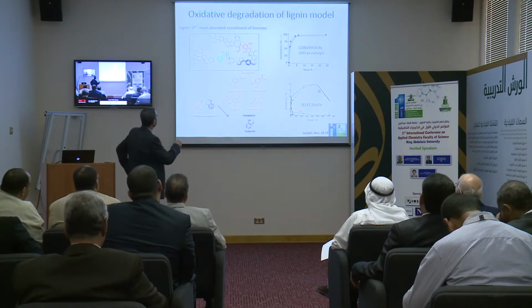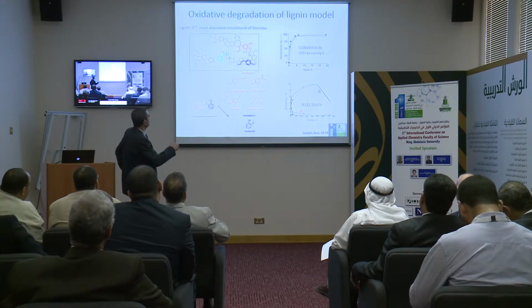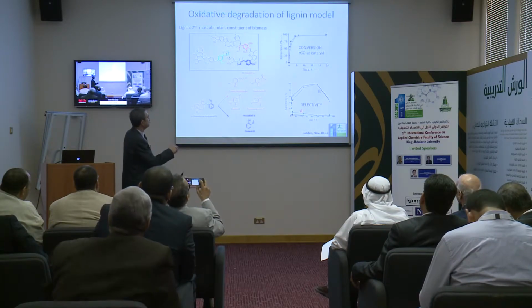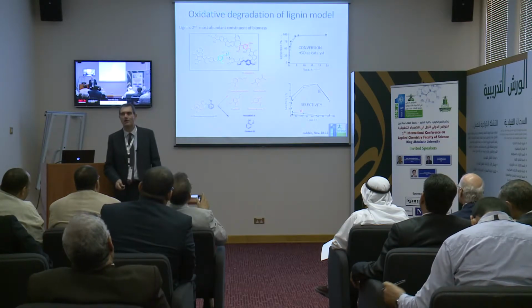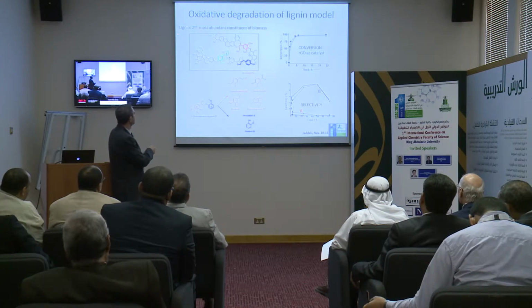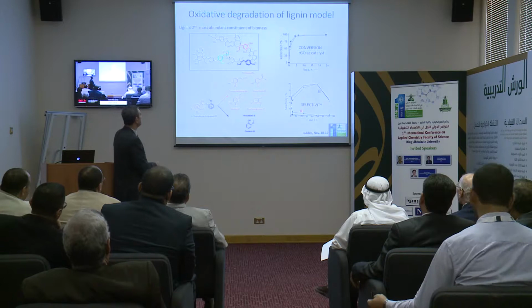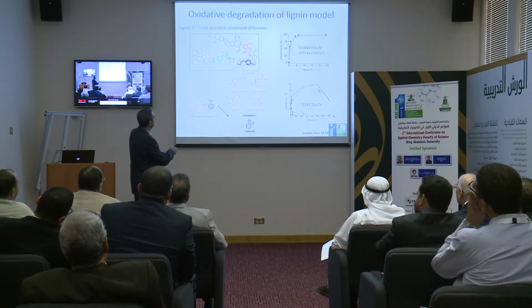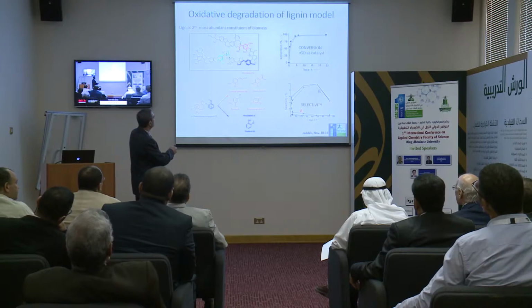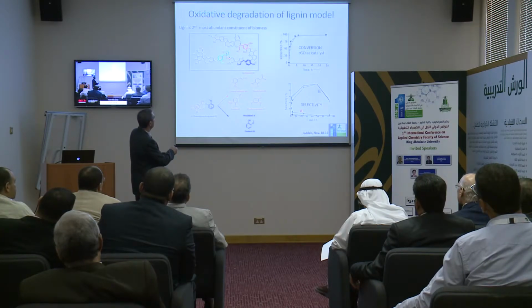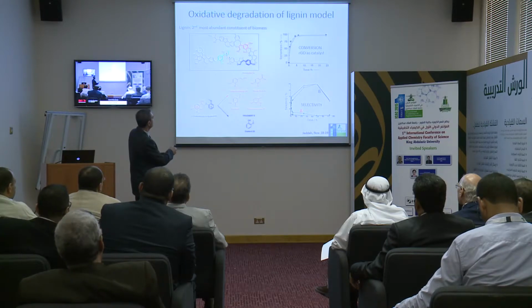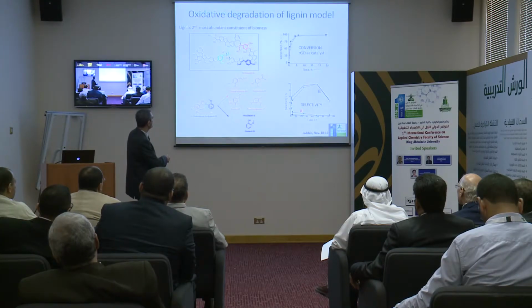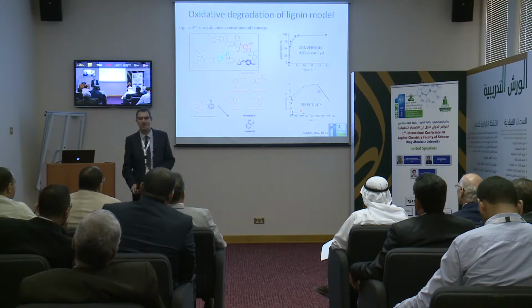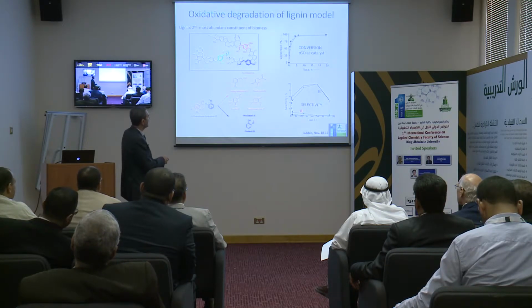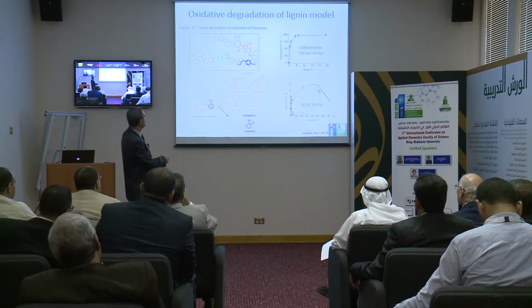We have used this ability of graphene for oxidation also to perform the degradation of lignin. That is one reaction that is very important in biomass transformation, because lignin is the second most abundant constituent in biomass, and lignin is a very complex polymer that contains many different unions, and one union that is here is a 4-beta oxygen bridge, the 4-beta oxygen bridge that has here in this model. So we were using this model as a way to make the depolymerization of lignin, and using just graphene, reduced graphene, what we observe is just very high conversion for the oxidation of this model.